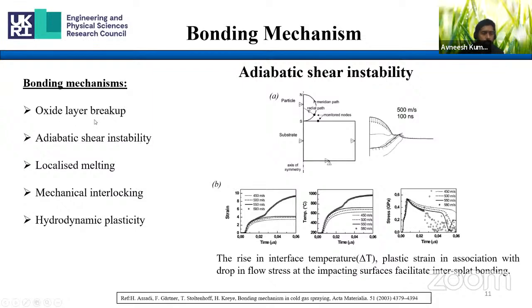The first one is oxide layer breakup. When the particle strikes the substrate with very high velocity, it breaks the oxide layer, if there is any on the substrate, and forms a new surface for bonding. Similarly, another bonding mechanism is adiabatic shear instability, which says that for a particle to adhere, there is a threshold value of velocity which it needs to reach. At that velocity, when it strikes, the particle deforms severely, along with a sudden rise in temperature, and the particle also loses its flow strength. When these three things happen together, this condition is known as adiabatic shear instability. Because of it, the particle flows from the contact, and jet-like features occur, which is the reason behind the bonding of the particle onto the substrate.